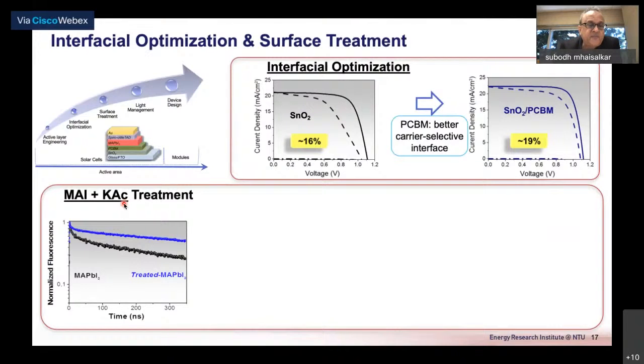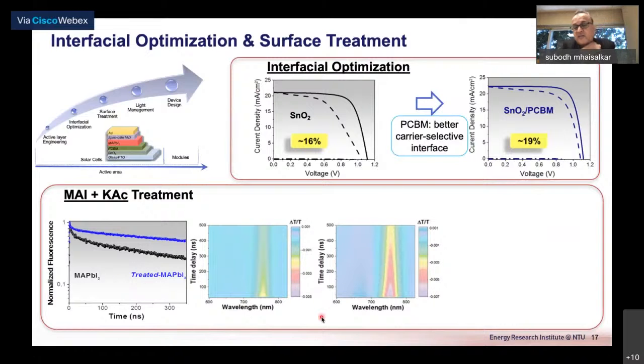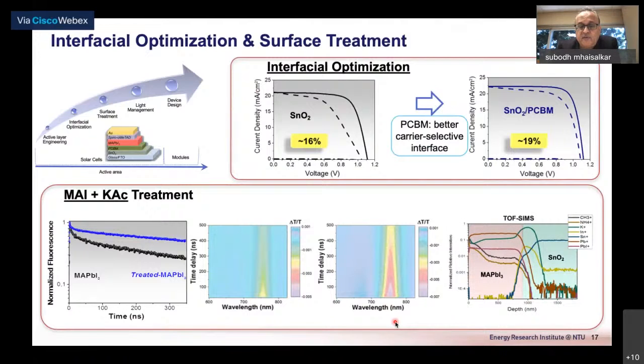It also helped improve the grain boundary conductivity of the deposited films, and this was verified by transient photoluminescence as well as transient absorption. And here you can see really that in the treated samples, which are on the right hand side, you can see a long-lived photo bleach excitation at 717 nanometers. We could also confirm the presence of potassium in the perovskite by using ToF-SIMS.